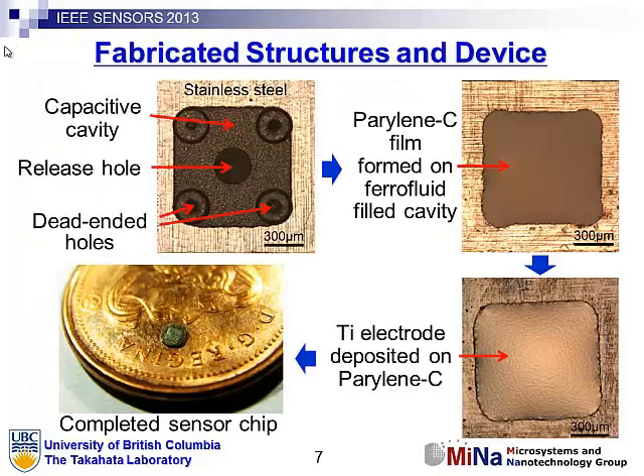So this is what the EDM chip on the top left looked like before any of the other steps. This sort of granular appearance in the center is from the EDMing. The stainless steel itself has, say, a surface roughness of many hundred nanometers. Then the picture on the top right is the Parylene coating after the ferrofluid is deposited, and then titanium E-beam deposited on top. And the final sensor itself is shown in the bottom left. So there were many sensors fabricated this way.